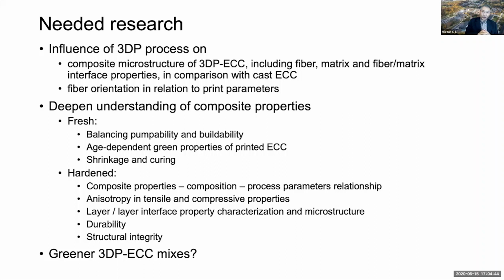We need to look at the age dependency of the green properties of printed ECC. This is almost a completely open area where very little has been done. But this is critically important in maintaining the integrity of the built-up structure as the printing is going on. And equally important are the subjects of drying shrinkage and curing. On the hardened properties, we need to look at the relationships between the composition, the ingredients, the composite properties, and the print parameters. I mentioned earlier the print parameters are going to influence the microstructure and therefore the composite properties. So these interrelationships are extremely important to investigate.